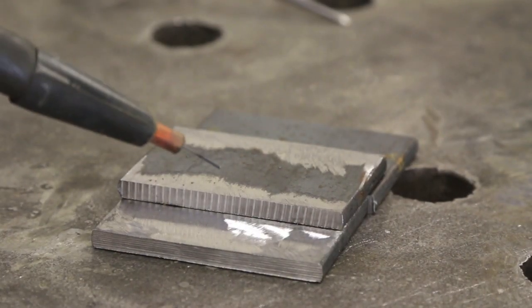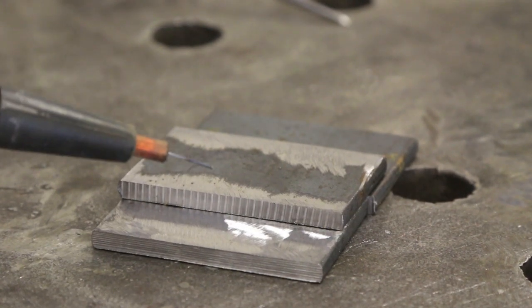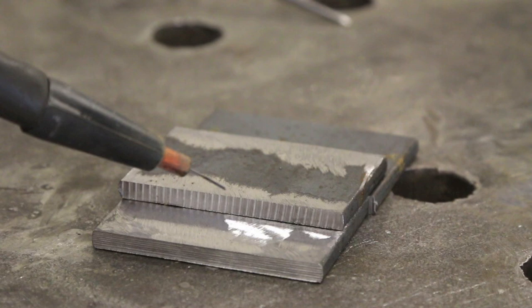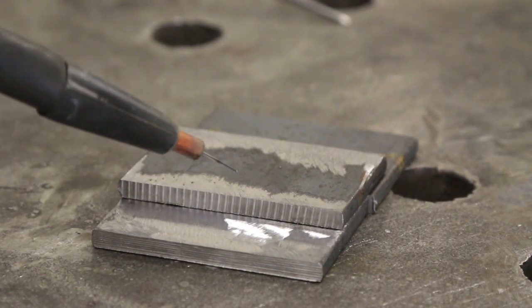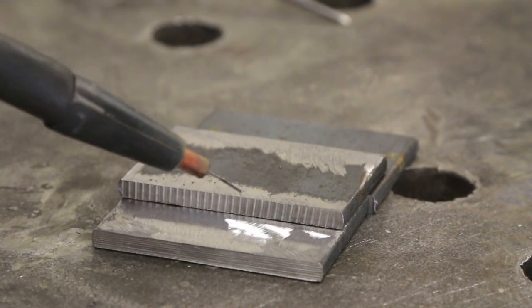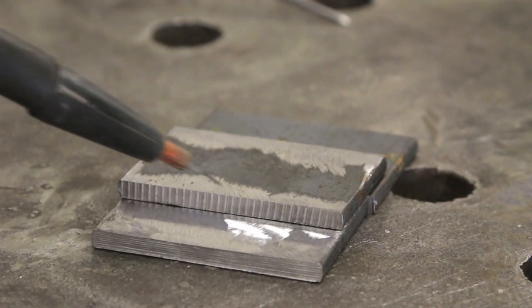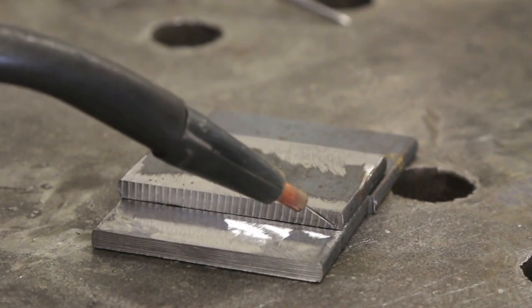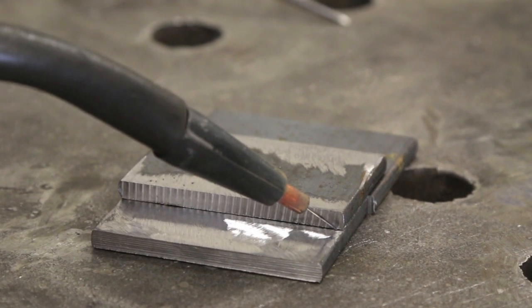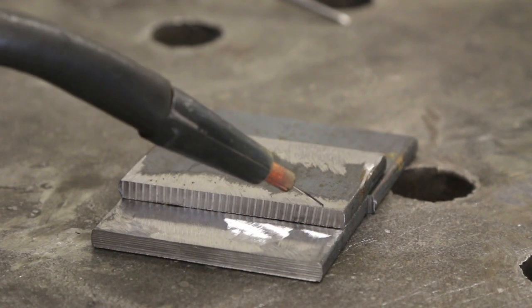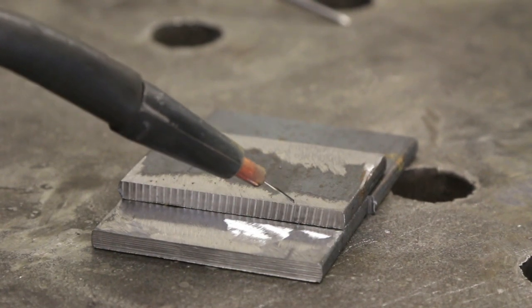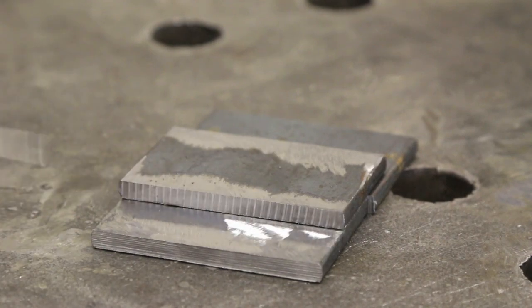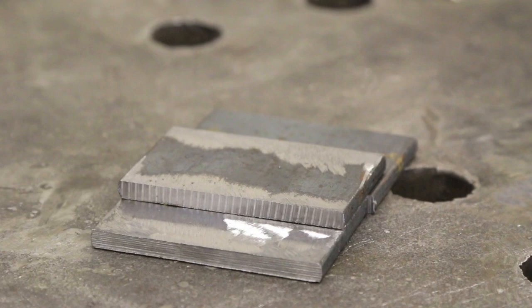Okay, before I get to welding, I want to come in here and show the actual gun and what we're going to do. First of all, notice that the stick out on here is somewhere between a half inch and three quarters of an inch. That's the manufacturer recommendation for this particular type of flux core. It's definitely a lot longer than you would do for MIG welding. And it seems to work better when you have it out this far. What I'm going to be doing is because this produces slag, I have to drag it. So I cannot push it. I have to start from here and I have to drag in a backhand angle, backward angle I should say. I'm going to aim primarily for where the two pieces join, right in the corner there. And because I'm going to have to try to swing this up a little higher, I'm probably going to do like a circular motion or an up and down, watching my puddle until my puddle just nips the top and then come down so that hopefully when all is said and done I'll have a nice 45 degree angle fillet weld from one side to the other. The first thing I'm going to do is I'm going to tack it on both ends. So let's go ahead and get that done.